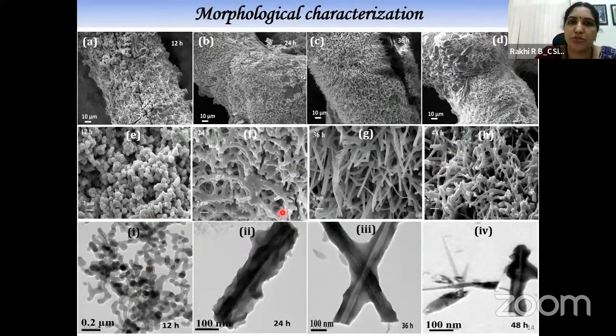Okay, let's see the microstructure. From our experience and whatever I have told, you should also have an intuition that the structure which is capable of holding maximum electrolyte will give maximum performance. Okay, so out of this, we cannot predict which surface will hold maximum electrolyte. Then we did microstructural analysis by TEM measurements, and cross-sectional images of the samples were taken, and we could find that the nanowires are in fact nanotubular forms of wires. Initially, we know that the spherical particles are the tips of some nanowires.